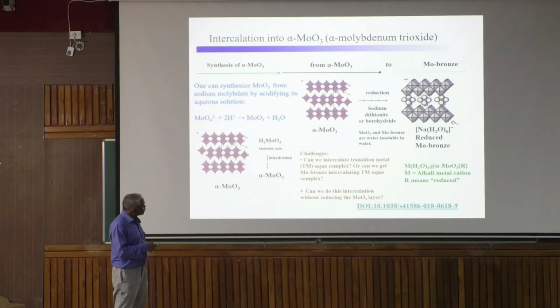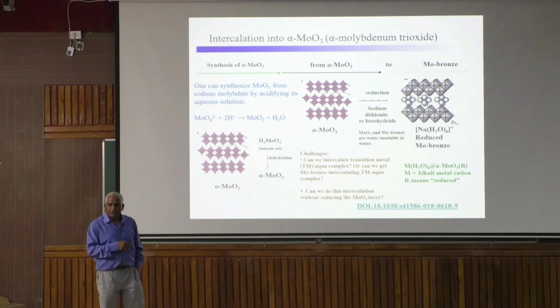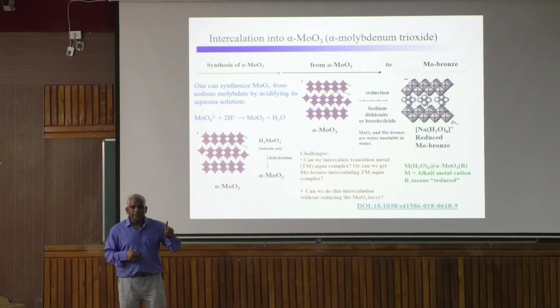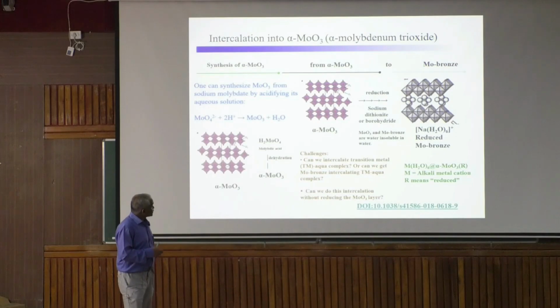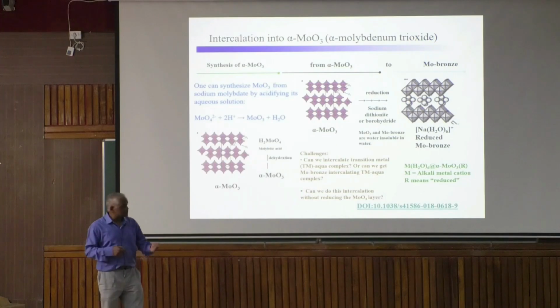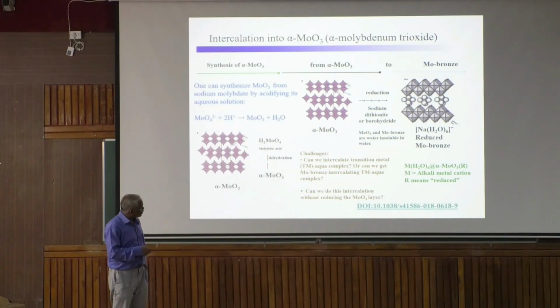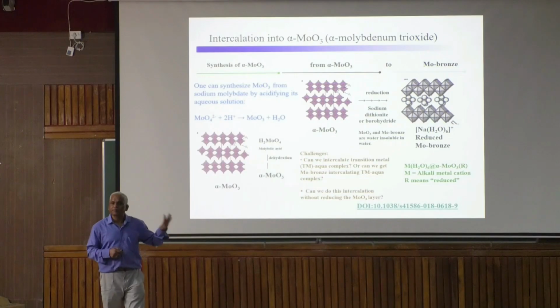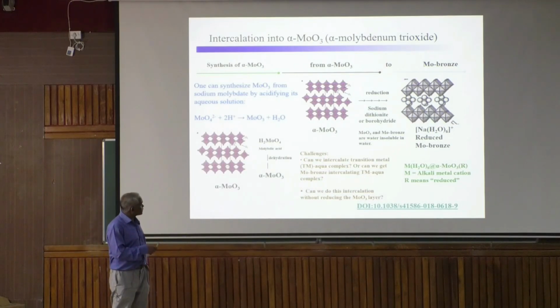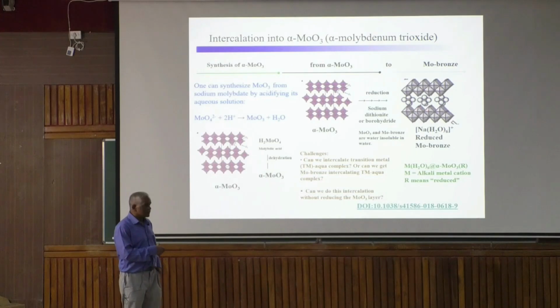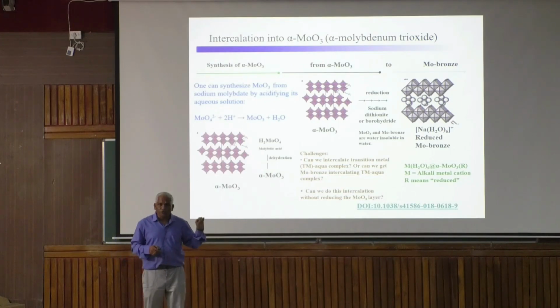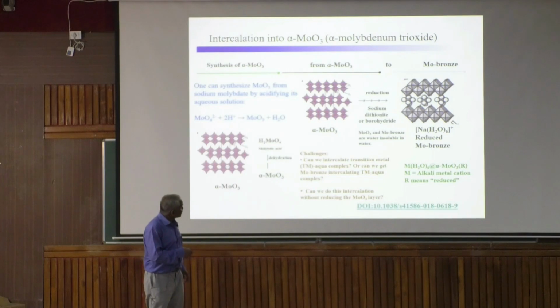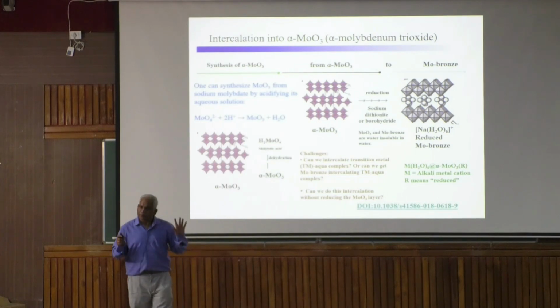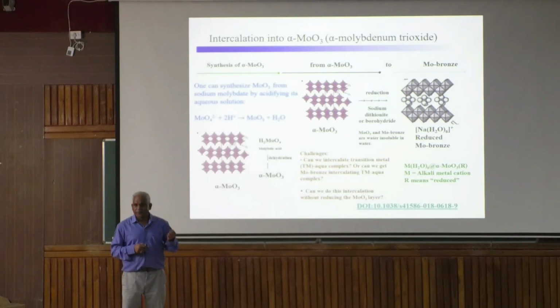It was a neutral molecule, now it is reduced. Molybdenum 6 goes to molybdenum 5. So molybdenum 6 is a d0 system, molybdenum 5 is a d1 system, an EPR active system. So it is a mixed-valent layer now. So that is a minus charge now. To counterbalance the negative charge, you need some cation. So a sodium aqua compound gets intercalated here. This is called molybdenum bronze. If you use potassium dithionite, you get a potassium aqua compound. Lithium dithionite, you get lithium. So all are called molybdenum bronze. That means what is molybdenum bronze? Reduced MoO3 intercalating an alkali metal aqua compound is called molybdenum bronze. Why bronze? They are shiny, lustrous, and electrically conductive. That's why it is molybdenum bronze.